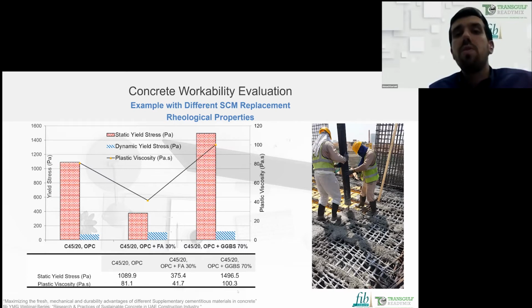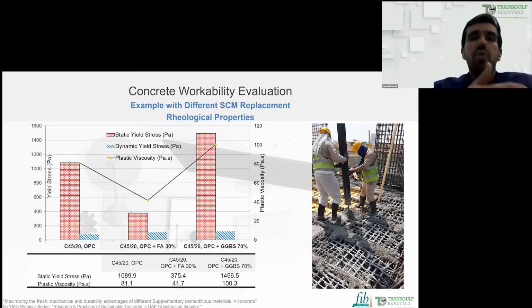While when you go for replacing the Portland cement by 70% GGBS, we notice an increase of around an additional 50% of the static yield stress of the control mix. Similarly for the plastic viscosity, it dropped to half for the fly ash concrete mix, and increased in the case of the GGBS mix. I'm going to highlight the reason during the coming study results.